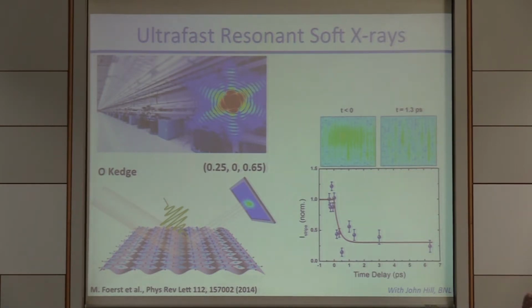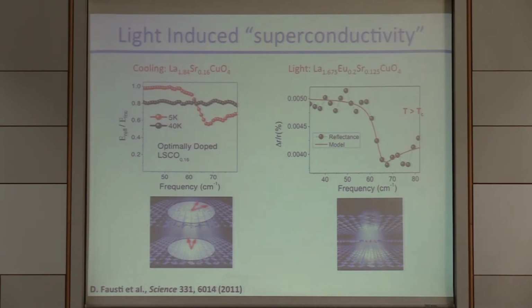Okay, so now I can think that with these ideas in mind, if I go now into my stripe cuprate and I measure with optics the low frequency reflectance, I should see the appearance of a plasma edge where the plasma edge was supposed to be if the system did not have stripes. And so this, again, took a while, but this is the transient change in reflectivity, with a number of details that I'm happy to answer if you're interested. But in principle, one can show that an edge in the reflectivity of the pumped system, in this material in which TC is effectively 0, can be induced if one melts the stripes with light.